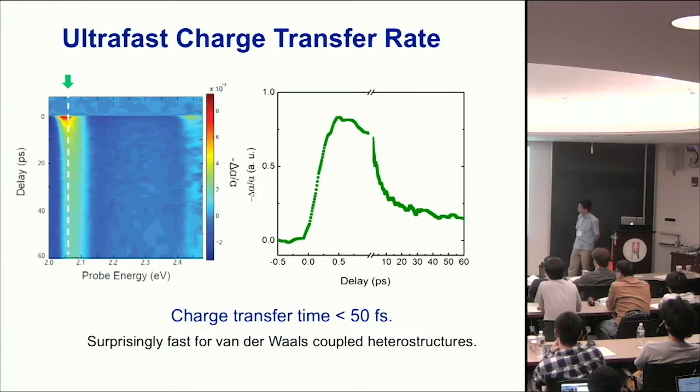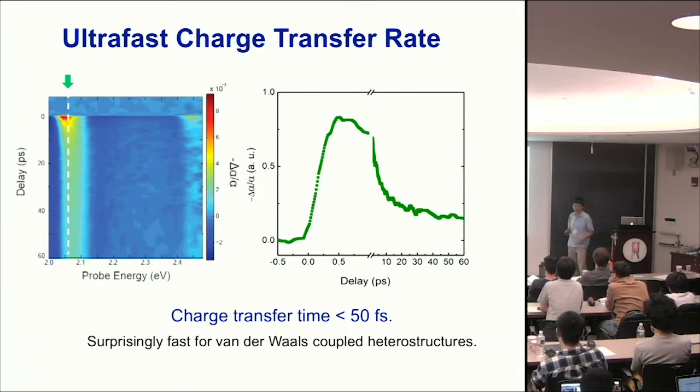Exactly. So we think it most likely involves emission of an optical phonon and then a jump to the other point. In particular, emission of an optical phonon usually can happen very quickly, in tens of femtoseconds, because the emitting of a large energy phonon tends to be very efficient.